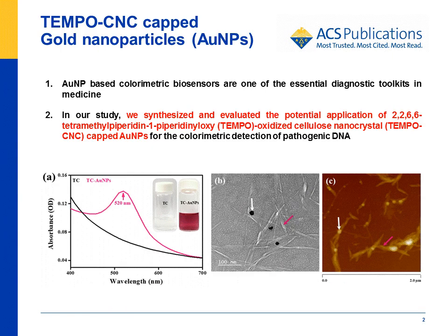Gold nanoparticle-based colorimetric biosensors have emerged as a robust diagnostic toolkit in medicine, mainly by exploiting their unique spectral properties upon particle dispersion or aggregation. It is well known that well-dispersed gold nanoparticle solution appears red in color, while a blue color is observed upon particle aggregation, which is greatly controlled by the capping agent used during AuNP synthesis.